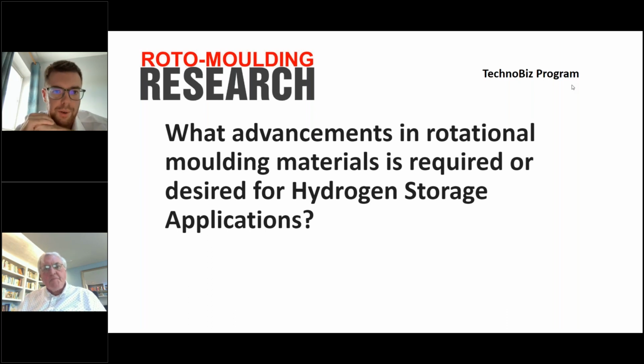Yeah. Absolutely, yeah. But then the 0.8 MFI material just barely even sintered properly. The foam it produced was practically useless, so there is a lower limit to that as well. Yeah. Absolutely. General roto-molding, yeah. The conclusion is that the rotational molding standard powders actually lend themselves quite nicely to atmospheric chemical blowing agent decomposition to produce foams.